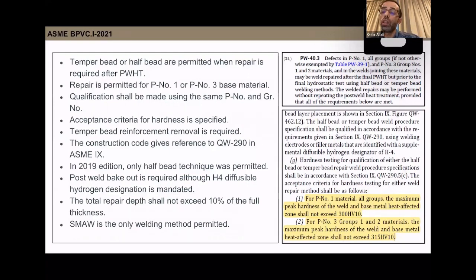So it's not like we're having a weld joint that is being welded and we don't want to do PWHT. No, this is when the PWHT is applied and when repair is required after applying the PWHT and before the hydro test. You want to do this repair, you can apply this technique, either half bead technique or temper bead technique.